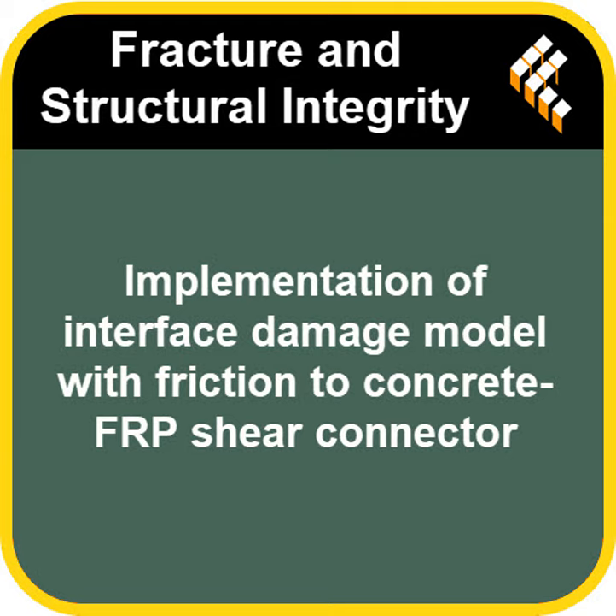The results were really illuminating. Initially, under low load, all the scenarios looked pretty similar on a force displacement graph. That's because everything was fully bonded. But as the load increased and debonding started, usually at one end, the interface began to slide. And that's where friction made a huge difference. It helped transfer the horizontal force, creating what they called a hardening effect. Basically, as it deformed, the friction kicked in, making it tougher to deform further. So friction doesn't stop the first crack, but it dramatically changes what happens next.